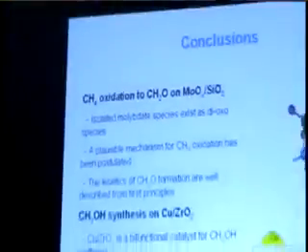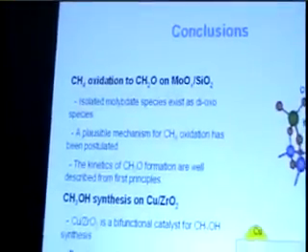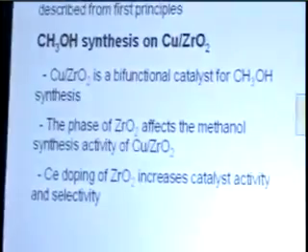And then in the last two examples, we first showed that methane oxidation will occur on these isolated molybdates, and that they have the structure shown here. They're dioxo, not monoxo. And this is partially reduced in situ. You form a peroxo, and that's what attacks the methane to make formaldehyde over here. And again, you can get the kinetics more or less right from first principles.